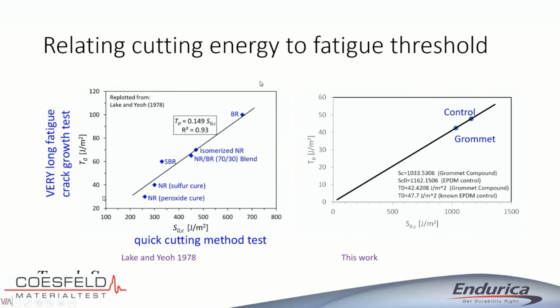These are the results from Lake and Yeoh, showing the correlation between the cutting method, right, the ISA test, versus running a very, very long crack growth test. Very strong correlation, goes right through 0, 0. This plot over here is for the grommet material, right? So you can see the grommet ends up with a threshold of 42 joules per meter squared.